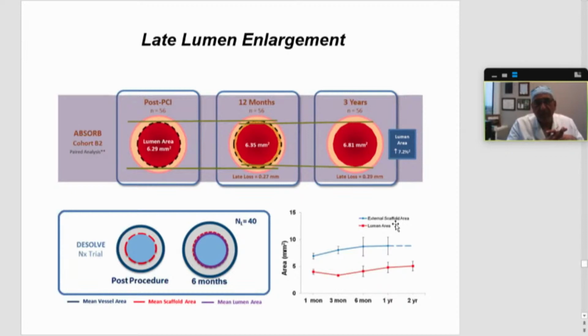As you can imagine, once the scaffold is absorbed completely, there is progressive positive remodeling of the vessel, without any associated late stent malapposition. And that can potentially lead to improvement of the vessel wall diameter, as you can see over the next 2 to 3 years after the BVS is completely absorbed. So I think this is a very, very interesting idea.